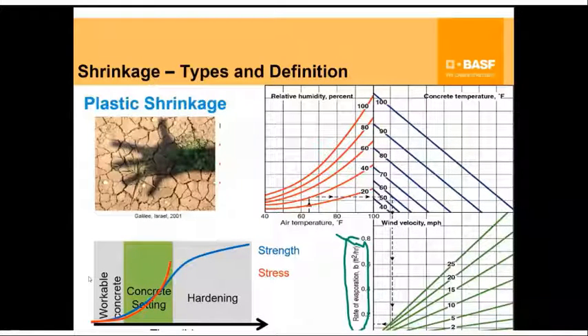As the red line crosses the blue line, which is the strength development, when the stress is higher than the strength, that is the point where you will have a crack. If you are always under the blue line, where the stress at any point is lower than the strength gain of your concrete over time, you will still have plastic shrinkage, but you will not have cracks.